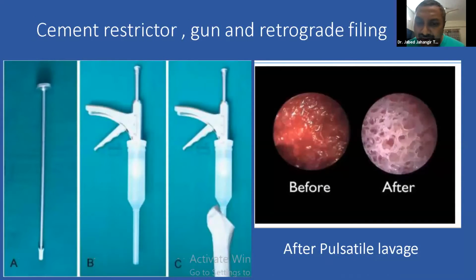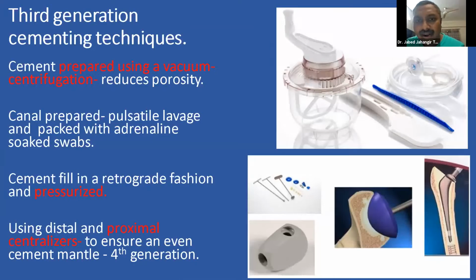You see, after a pulsatile lavage, the bone is so clean and the trabeculae is clearly seen. And with this trabeculae, there is a micro interlock of the bone cement and bone. So in 3rd generation technique, there is vacuum mixing which reduces the porosity, and integrity of the bone cement is much better, and pressurization is one more important thing. You have to maintain pressurization to overcome the femoral canal blood that tries to displace bone cement in bonding with bone. So the use of centralizer is another important thing of modern cementing. The proximal and distal centralizer, when we use it, is sometimes called 4th generation cementing technique.